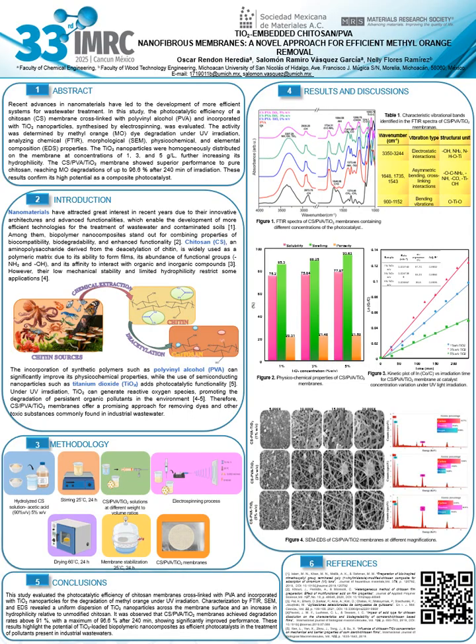and carbon-oxygen stretching vibration, while peaks at 1,364 to 1,248 per centimeter correspond to carbon-nitrogen stretching and carbon-hydrogen bending vibration. Importantly, the band around 900 to 1,100 per centimeter, assigned to titanium-oxygen-titanium and titanium-oxygen-carbon vibrations, was more intense in samples with higher titanium dioxide loading, confirming the incorporation of titanium dioxide and its interaction with the polymeric network. This chemical bonding is significant because it prevents nanoparticle leaching during photocatalytic operation, increasing the stability and reusability of the membranes.